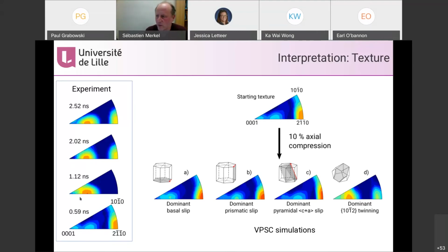So what's happening when we go from a texture at 2-1-10 to this one, 30 degrees away from compression, from C, is the grains are twinning. The grains are twinning under the effect of shock, under the effect of plasticity. You get grain reorientation through twinning. Then later in the shock, we get an increase again of the starting texture, and it's just due to the shock that's moving through the sample. There are new grains of HCP being generated with a starting texture, and then they slowly twin.